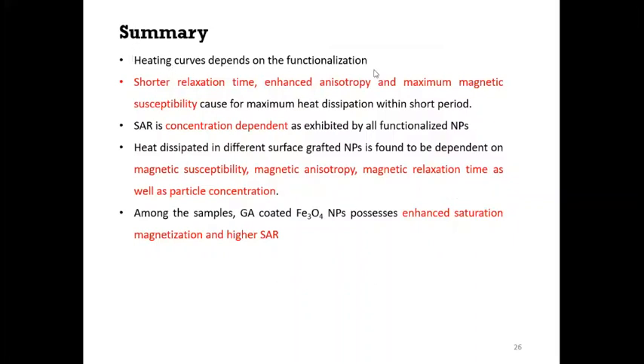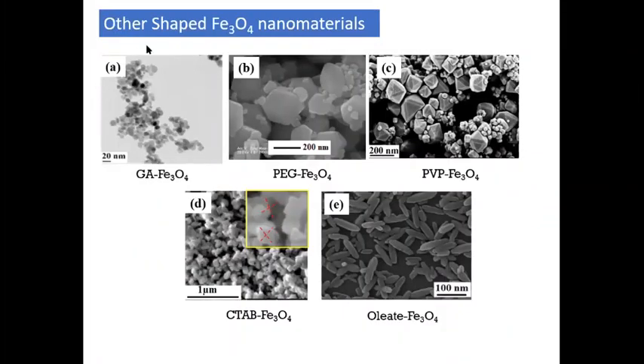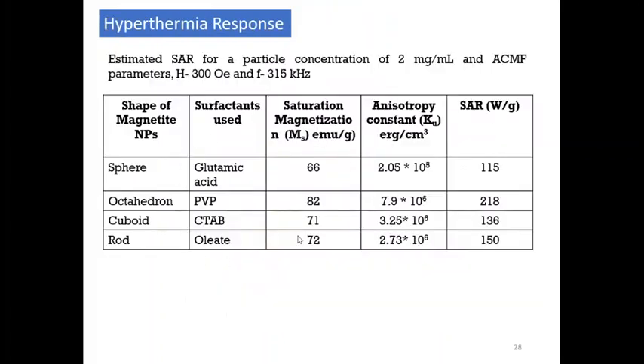So in summary, the heating curve depends on the functionalization, Néel relaxation time, effective anisotropy, and maximum magnetic susceptibility, which cause maximum heat dissipation within a short period of time. SAR is also concentration dependent, and the heat dissipated in different surface grafted nanoparticles is found to depend on the magnetic susceptibility, magnetic anisotropy, magnetic relaxation time, as well as particle concentration. So all these parameters have to be optimized to get better behavior of the nanomaterials. Apart from that, we have prepared nanomaterials of different size and shape: spherical, ellipsoid, truncated octahedrons, nanorods, and cubes. It has been found that because of different anisotropic constants, the SAR value also has different values.